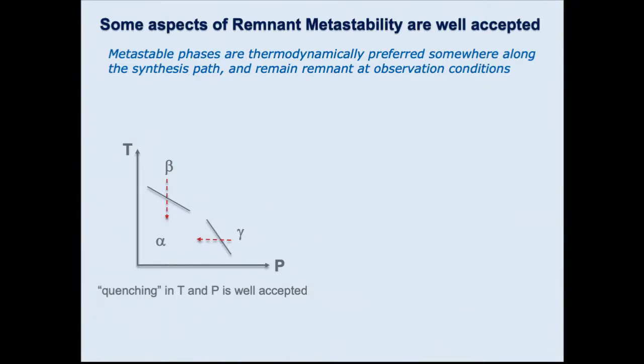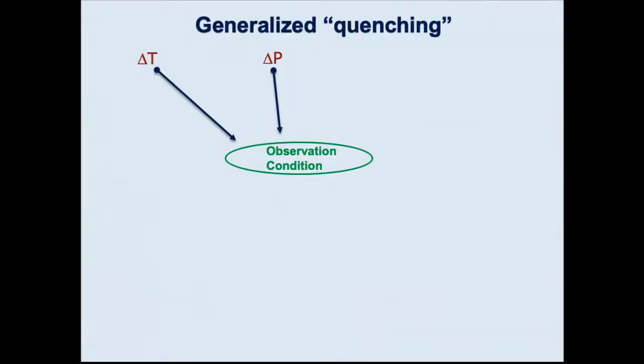So what we want to do is we want to generalize quenching in other variables, right? That's the whole idea, that these conditions where you make things is not just a matter of temperature and pressure. There are other thermodynamic variables that control your boundary conditions, and under those variables you create the stable state, and then you quench it in some variable space. Okay, so generalized quenching, of course, delta T and delta P, but we obviously know that you can grow things metastably under strain, right? You can do epitaxy and then retain it even if you release the strain.